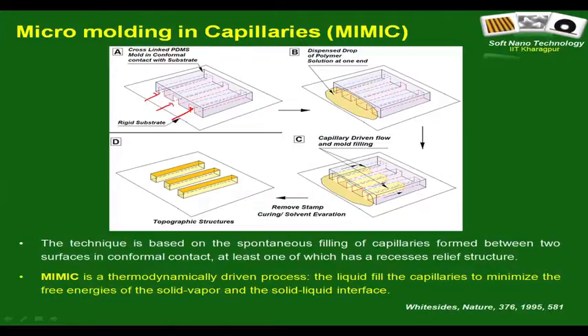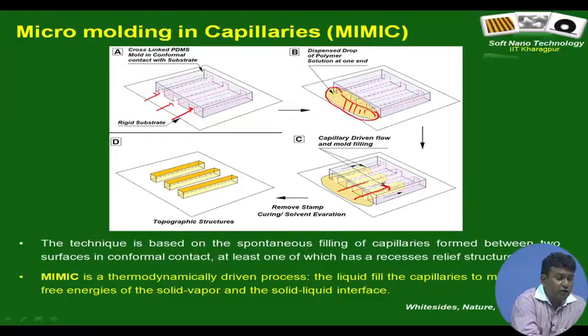What you do now is you take a dilute solution of the polymer, or the material with which you would like to create the structures, and simply dispense it at one of the open ends, right. Now, if the stamp wall is wettable, which you can always do by controlling the surface energy, maybe I will give you some recipes how to do that later, what will happen? There will be capillary driven flow along each of these capillary micro channels, and as a result the liquid meniscus will move. So, eventually all you need to do is let the solvent evaporate, and then you get strips of this polymer or the soft materials along the contours of the stamp.